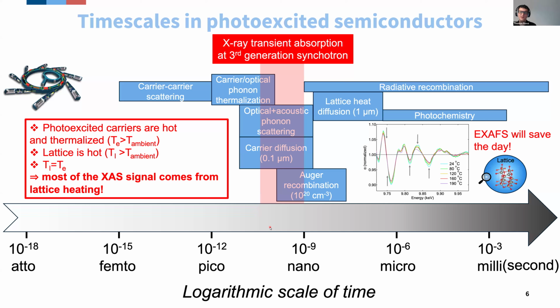So when your X-ray pulse arrives at your sample and records an X-ray absorption spectrum, a lot of things have already taken place in your semiconductor after it has absorbed the optical light. There are typically two processes that happen way, way before the 100 picosecond mark. One process is the carrier-carrier scattering. So all your photoexcited carriers now have thermalized, so they have collided a lot with each other. And because they have collided so many times, they achieve a distribution that can be described by a single temperature.